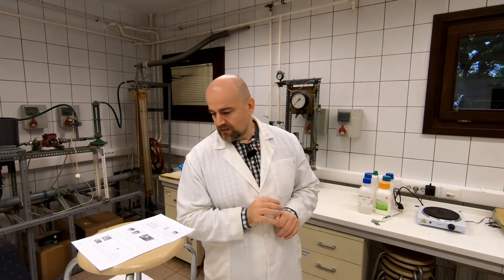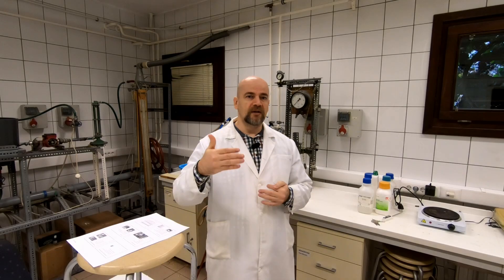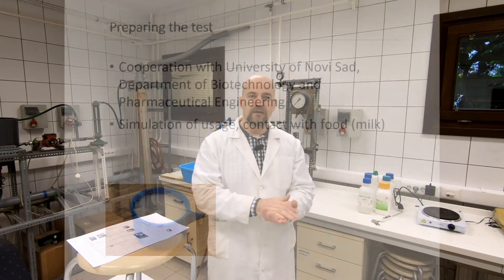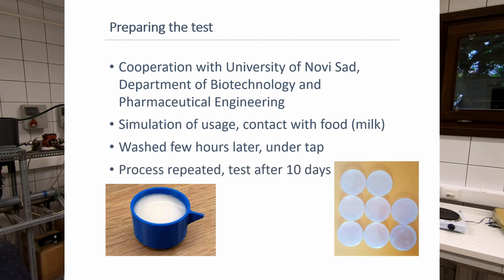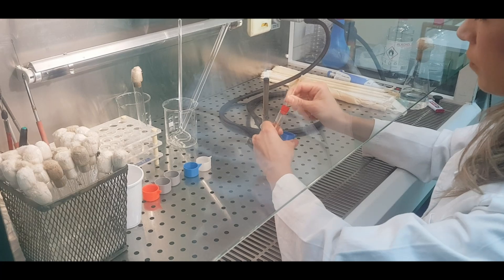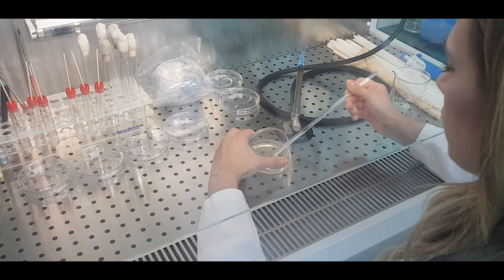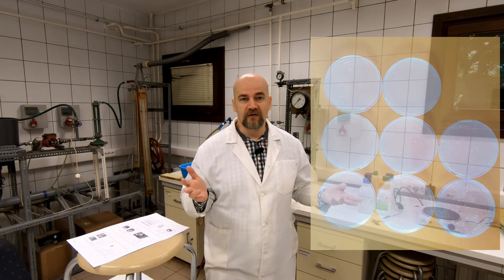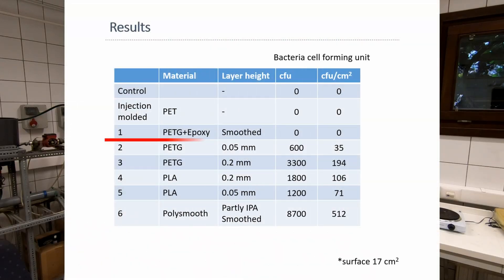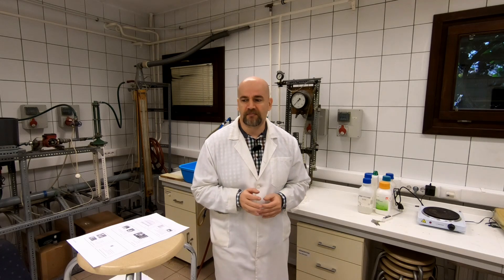In cooperation with the University of Novi Sad, Department of Biotechnology and Pharmaceutical Engineering — thanks to my colleague Jovan Grahovac — they prepared an experiment simulating food contact. They used milk, placed it in the cups for a few minutes to hours, then washed only under a tap, not in a machine. After a few days they repeated this process. After 10 days simulating kitchen use, they checked the bacteria and yeast that grew on the surface. And this is the result. Analyzing the table, neither PETG nor PLA showed good results. None of these uncoated materials are recommended for food contact 3D printed objects because it's very dangerous.